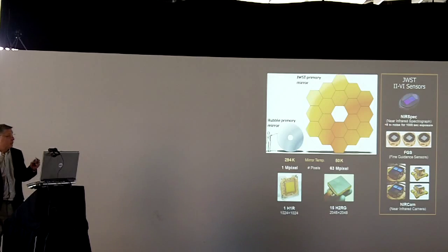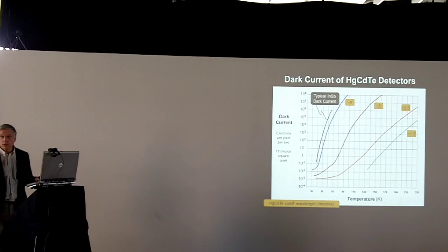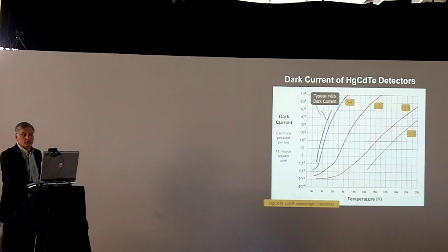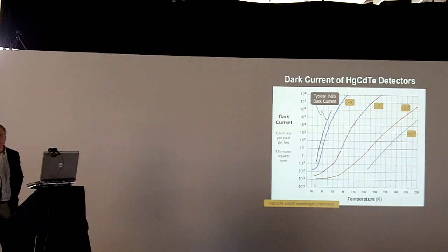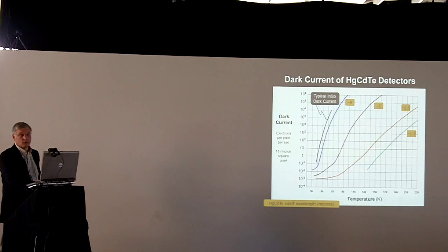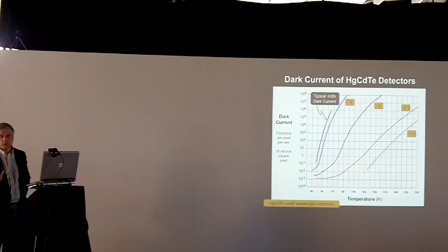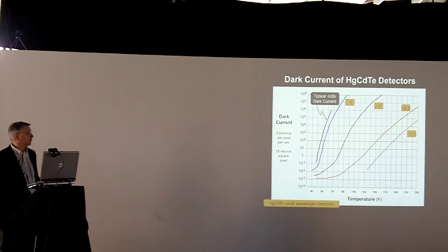And one reason is if you get HgCdTe materials very cold, the dark current's extremely low. This is temperature on the horizontal scale, a linear scale, and this is dark current, logarithmic, in number of electrons per pixel per second. And the James Webb Space Telescope is going to operate at 37 degrees Kelvin. And so that's right about here. And you can see here for 2.5 and 5 micron cutoff detectors, you only get a few electrons per pixel per 1,000 seconds. This is 10 to the minus 3 here. So dark current is really not an issue, it's just readout noise. And so you basically don't have to worry that much about dark current if you can get things cold enough.